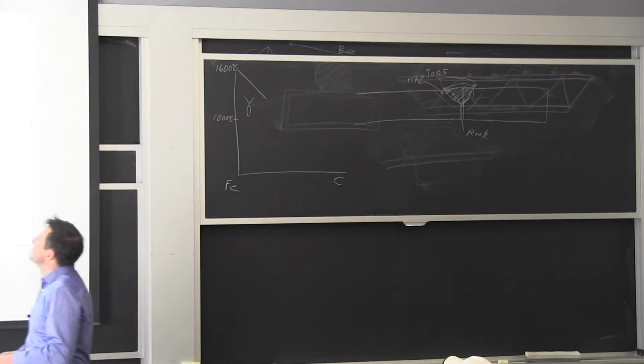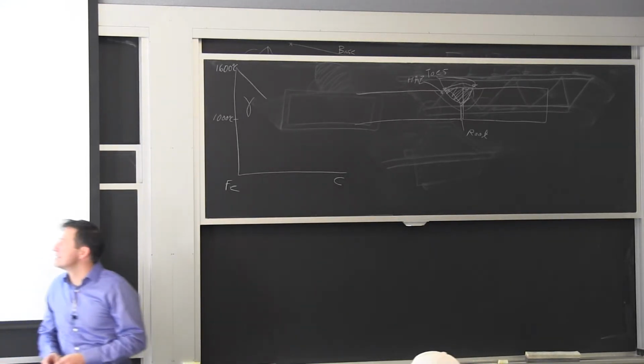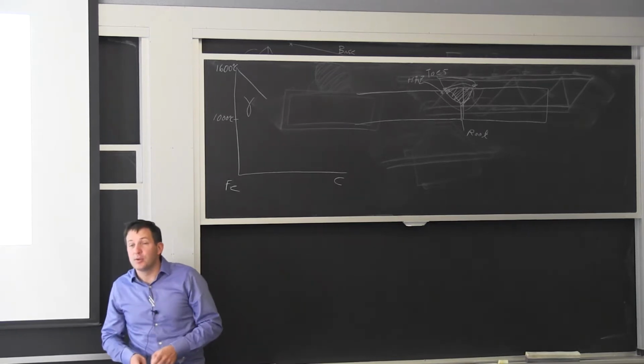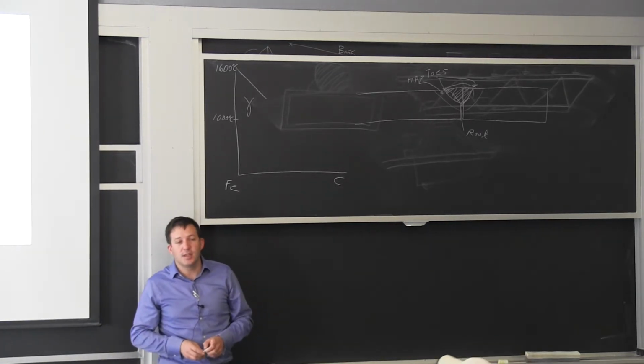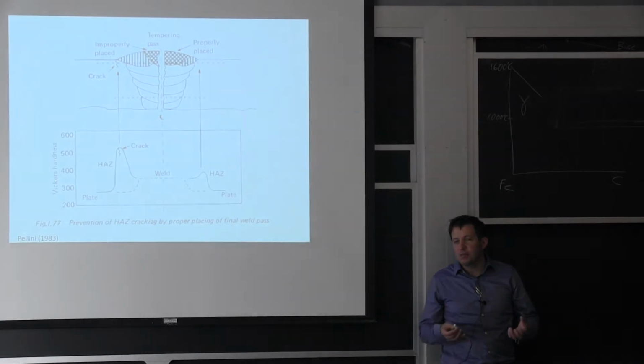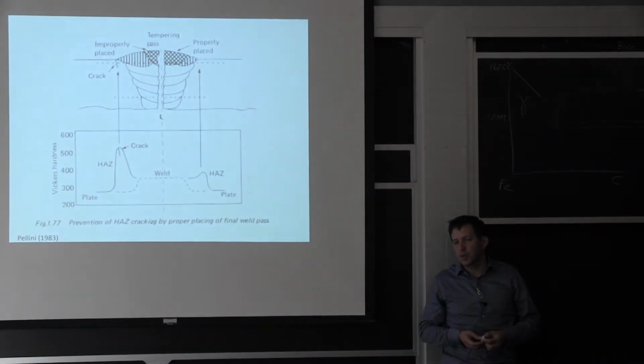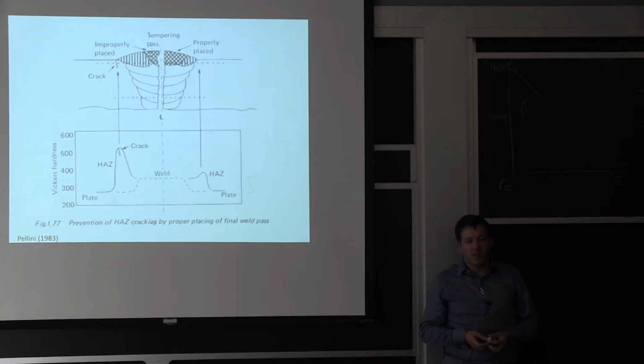So for steel, the increase in the hardness, yes? So post-weld heat treatments, does that dampen out that stress profile that you have significantly? Yes, you do both. That's a good point. So you can get a stress relief if you're doing the post-weld heat treatment. The main reason we do it is to try to temper any martensite we could be generating if we're talking about steel. But at the same time, before we get there, we're relieving the residual stresses.